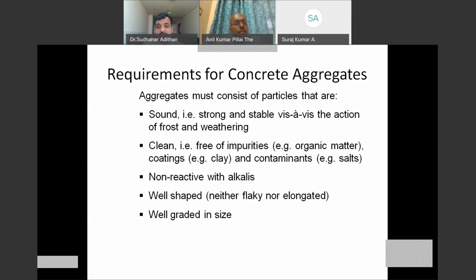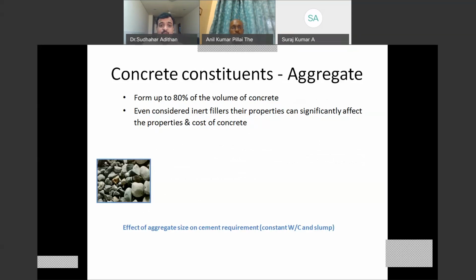And the shape and size of the aggregates matter a lot, more than the engineering qualities of the aggregate itself. As we just saw, they form up to 80% of the volume of concrete. They are ideally assumed as inert fillers, as long as you want to consider them to be very inert and non-participating in the system. But modern day research is finding a lot of information that aggregates can also participate in the hydration and result in different performance of the concrete system as well. So it is not always imperative that the aggregates have to be considered as inert only.